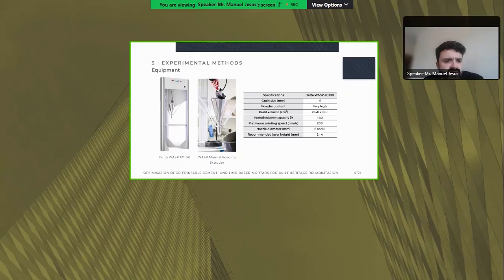So regarding the equipment that we used and that we have available in our laboratory, we began the experimental campaign by defining the operational parameters. A Delta WASP 40100 was used, and it imposes some specific material constraints. Since the nozzle diameters are quite small, we have two nozzle diameters of 0.6 and 0.8 millimeters, the maximum aggregate size is limited to 1 millimeter. So this required a higher concentration of fines in the mixture design to prevent the clogging of the extruder.